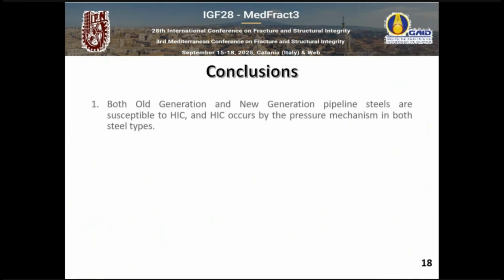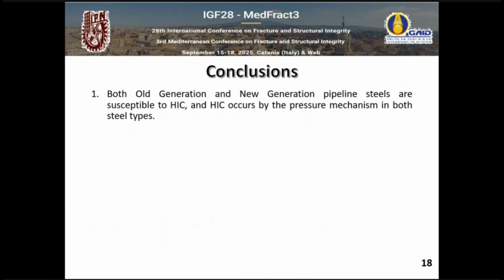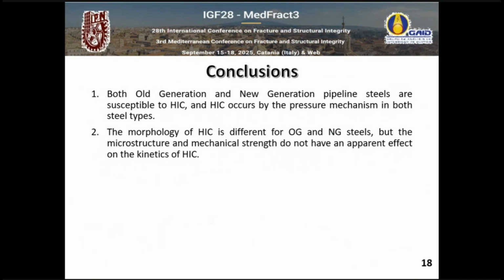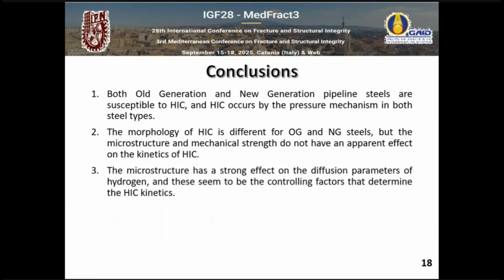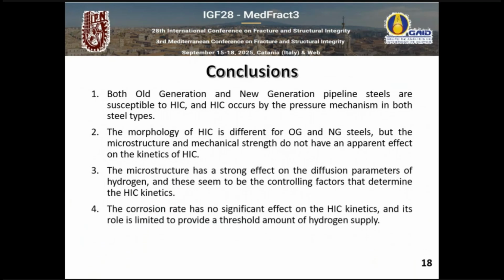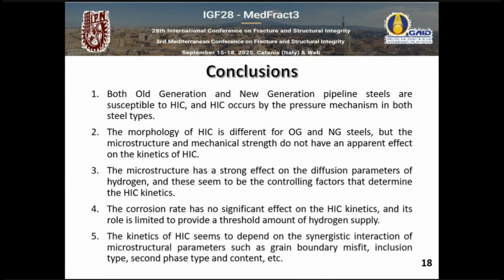So in conclusion, we can say that both old generation and new generation pipeline steels are susceptible to HIC. HIC occurs by the pressure mechanism in both steel types. The morphology of HIC is different, but the microstructure and mechanical strength do not have an apparent effect on the kinetics. But the microstructure affects the diffusion parameters, and this seems to be the controlling factor. Again, we didn't see any effect of the corrosion rate.